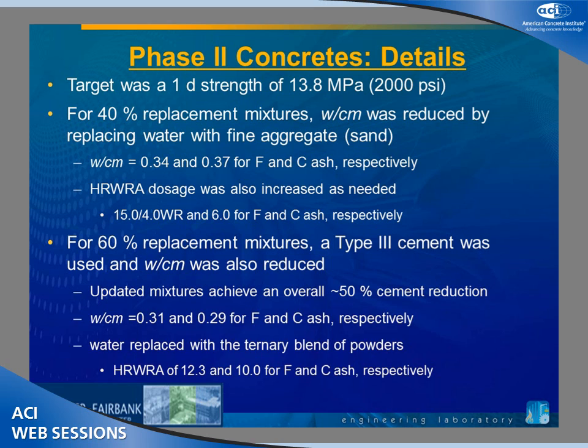For 60% replacement, replacing water with sand wasn't going to get us there in terms of the strengths. So we also switched to a type 3 cement to get the early strengths. And we replaced the water in this case with the blend of ternary powders. Because we're putting more powder in, even though we're pulling out 60% of the cement, by the time we increase the powder content relative to the control, we're not getting a 60% cement reduction, but we are still getting a 50% cement reduction.